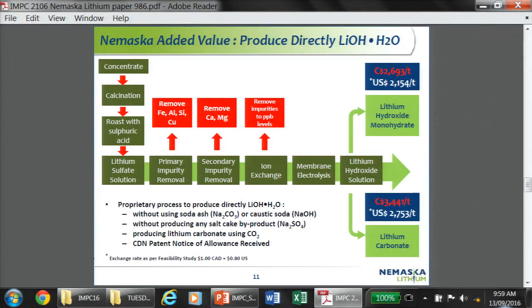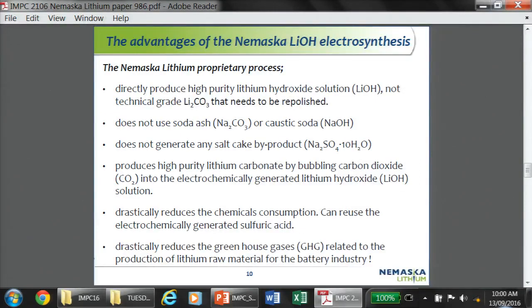Basically, it's quite similar to the chloralkali industry. Silica and calcium, because the combination of both creates calcium silicate or magnesium calcium silicate in your membrane. When silica and calcium or magnesium meet together in the membrane, they form a precipitate. If you have some ppm of silica, it's not so bad. If you have some ppm calcium, it's not so bad. But if you have both, that's not a good thing. So you need to be very good on the purification, and it's a problematic very similar to the chloralkali industry. Thank you very much.